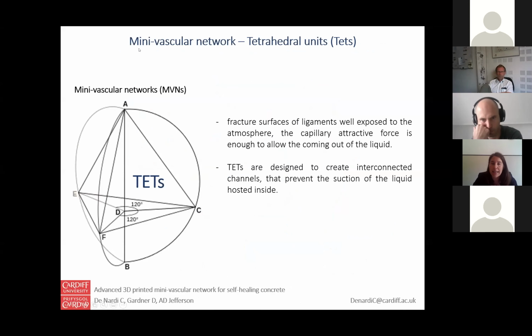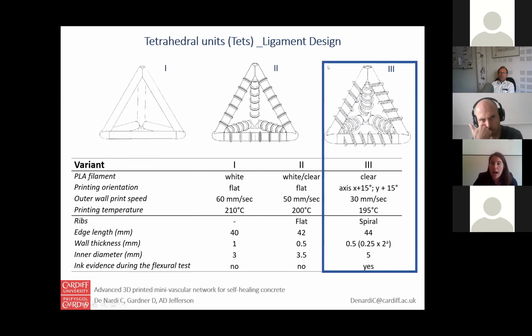So when, as I said, the matrix is made of concrete, the mini-vascular network has this particular shape, which is a regular tetrahedral unit, and it gives good properties in terms of positive capillary force enough to allow the coming out of the liquid, and at the same time the interconnected channels prevent the suction of the liquid hosted inside as well. So the initial stages of this study involved 3 variants.